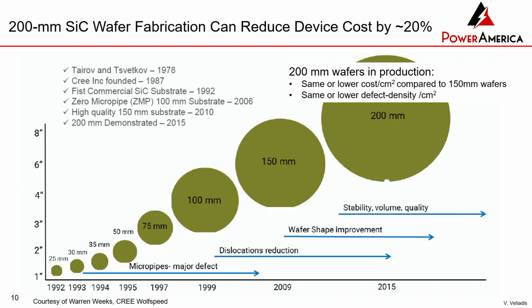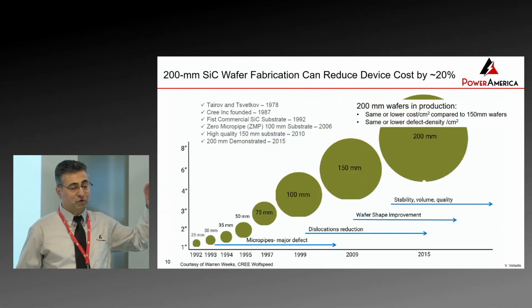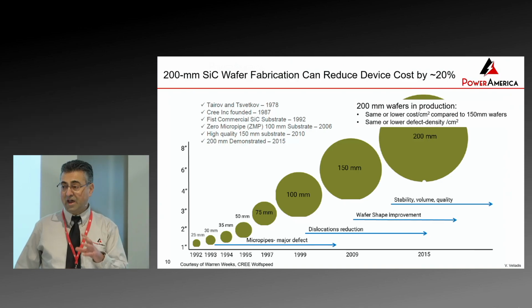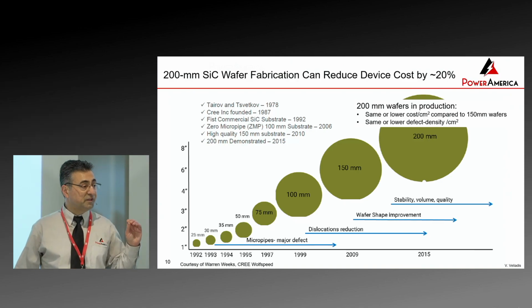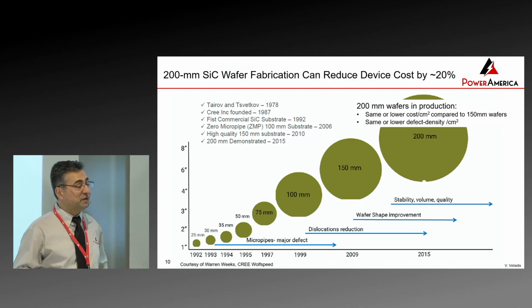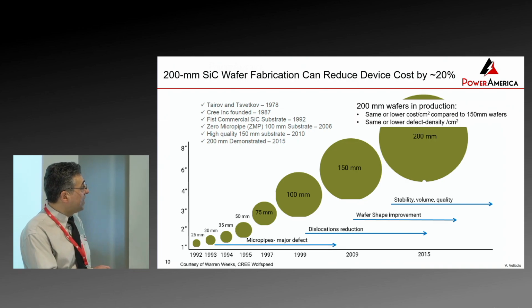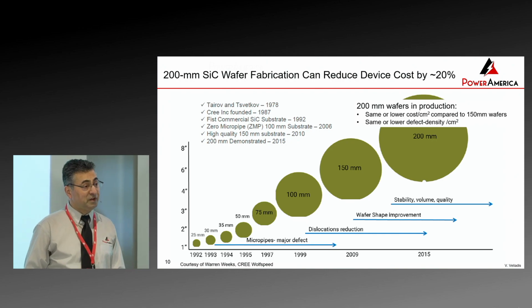And one can say, okay, if I go from 150 millimeters to 200, I'll have 40% more devices. That's a 40% reduction of cost. That's not going to be the case, of course, because we all know that whether you process a 150 or 200 millimeter wafer in the fab, the cost of processing is approximately the same, but the cost of material now will be a lot more expensive. When I was talking to Wolfspeed, they told me that in releasing 200 millimeters, the goal is to have the same or lower cost per centimeter square compared to 150 millimeter wafers, and of course, same or lower defect density.